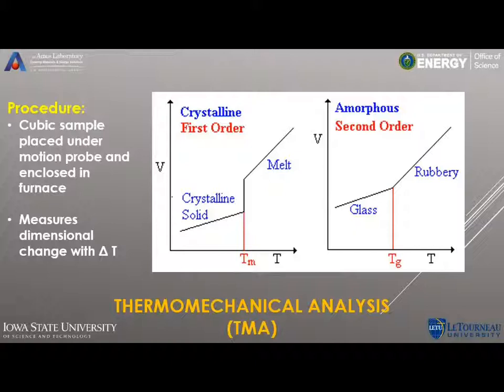Here you can see representative graphs. On the left-hand side, you're actually passing the melting point. You can see that there's a sudden volume change, and that's indicative that the sample is melting altogether. And here on the right-hand side, you can see where you're passing the glass transition temperature, the TG. And so the slope is just increasing in angle, or that is, the volume's suddenly increasing more as the temperature goes up. So it's passed into rubbery phase at that point.